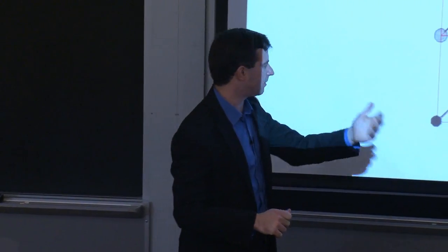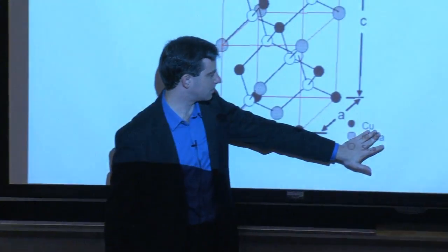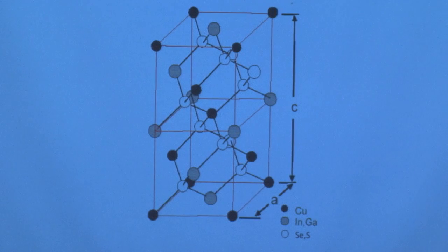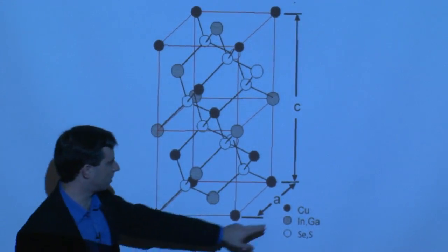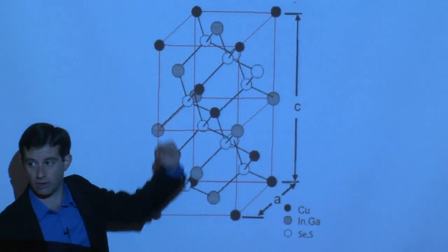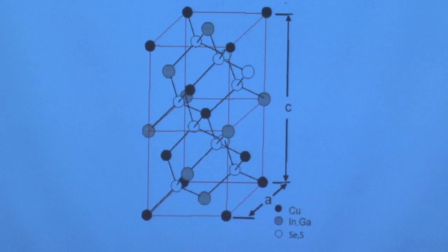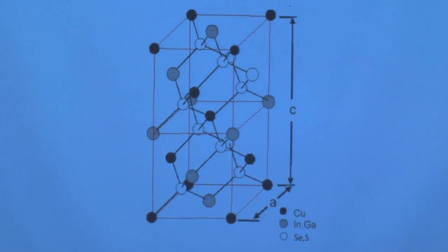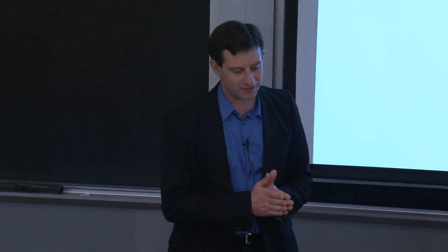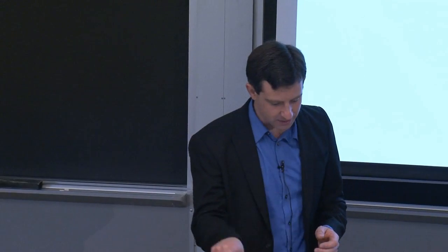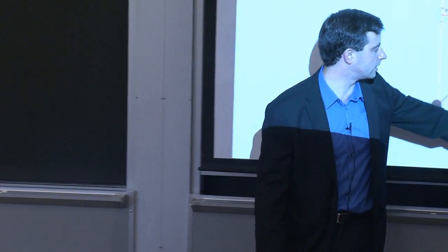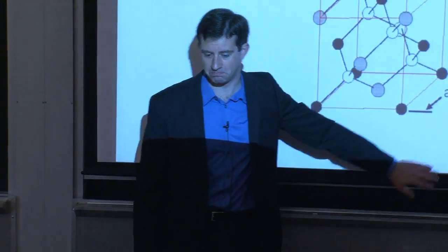So copper being on the far right-hand side of the 3d elemental series has a smaller atomic radius compared to, say, iron or manganese or titanium. And as a result, it could move fairly easily throughout the lattice if it is present in a charged state, if you have, say, Cu+, and a large electric field distributed across a thin film solar cell device. So copper sulfide devices ended up degrading quickly over time, and it was realized that some heavier elements needed to be included to stabilize the crystal structure.